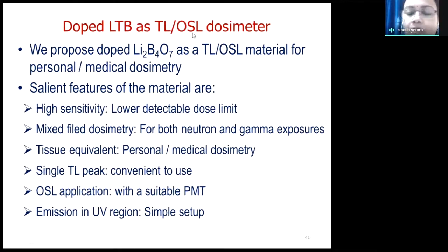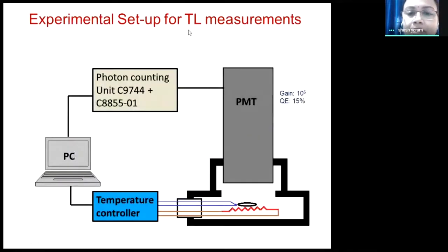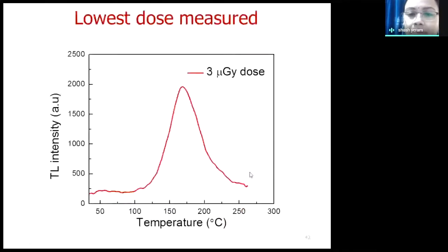This is TL/OSL: thermal stimulation, that is thermoluminescence, and optically stimulated luminescence. For thermoluminescence, very small chips of these crystals are used for the dosimeter. We put it on a temperature control heater, and we have a photomultiplier tube which records the luminescence coming from it. As it is heated, it is plotted, and we get this kind of a curve.